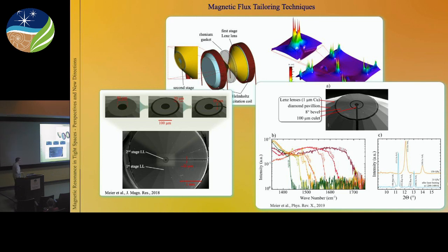Again, if we do that on both sides, we have to deal at some point with 6 lenses, which is a bit messy, especially in the preparation stage, because as you can imagine, these copper layers are quite fragile. But if you are able to prepare such a cell, you can pressurize up to, well, we reached 200 GPa recently with a pair of 100 micron diamonds.